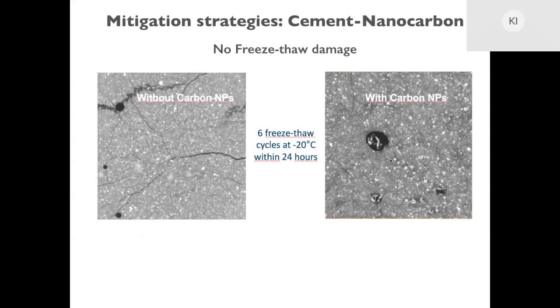And all of them were saturated with water, 100%. So in one case on the left, we see clearly macroscopic cracks that have percolated the sample. In the other case, maybe there are nano cracks, but they have not percolated the sample yet. So of course, it's very interesting to find out after how many cycles we will observe damage in the case with the carbon nanoparticles. But in the same conditions, we definitely have, in one case, a fully cracked paste, and with the carbon nanoparticles, we don't observe macroscopic cracks.